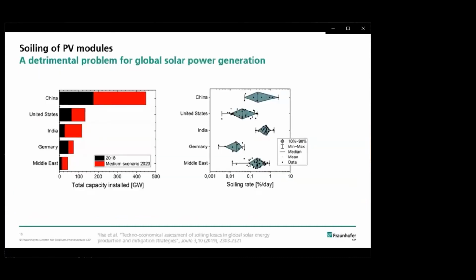In order to better understand the global impact of soiling on solar power generation, the graph on the left is showing the total installed PV capacity in gigawatts for major PV markets, including China, the United States, India, Germany, and the Middle East, for 2018 and expected values for 2023. On the right side, the corresponding soiling losses, as reported from literature, are given in percent loss per day. A soiling rate of 1% per day means that after 3 days without cleaning, you will have 3% total power output loss. There's a huge variation of soiling rates between, but also within the countries. However, one can state that by 2023, more than 500 gigawatts of PV will be installed in soiling-prone areas.